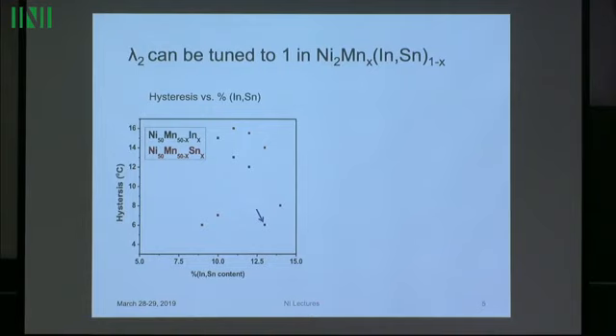It's been tuned by lowering. This is hysteresis versus composition, replotted as hysteresis versus the middle eigenvalue. And you see again the sharp drop. It only goes down to 6 or 8 degrees hysteresis. So this has, in fact, been made smaller.